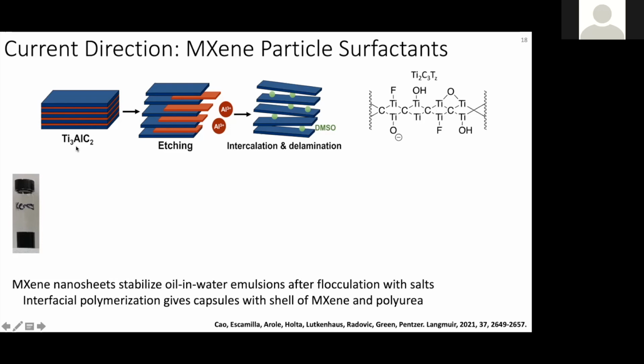So MXenes are typically made by taking a MAX phase. So luckily my colleague Miladin Radovic is an expert in making new MAX phases, but here we just use a very, I would say, traditional MAX phase. And you treat this with HF and lithium chloride normally, which removes the aluminum from the interlayers, and then you treat it with DMSO, some mild sonication, and this delaminates the nanosheets. And so MXenes have a negative zeta potential.